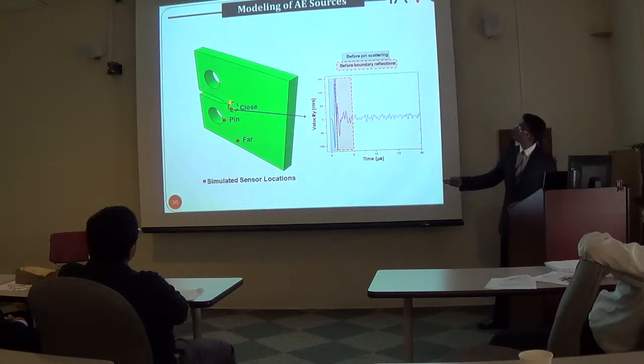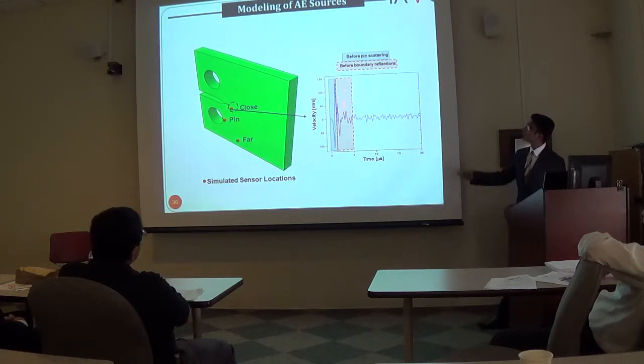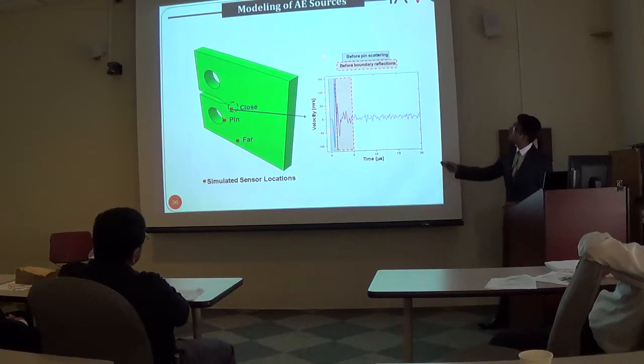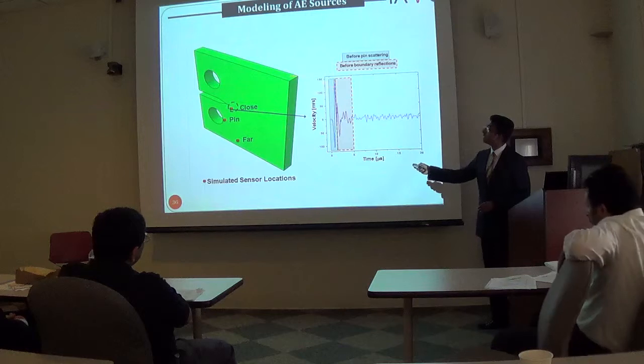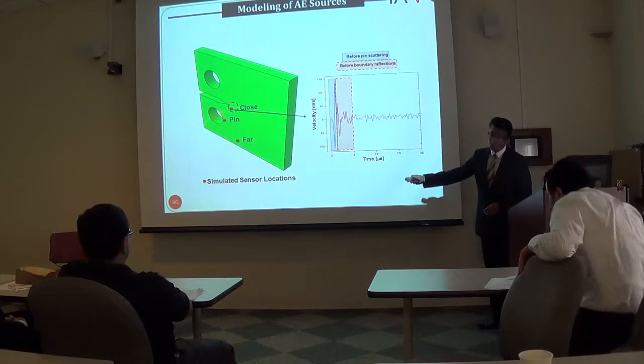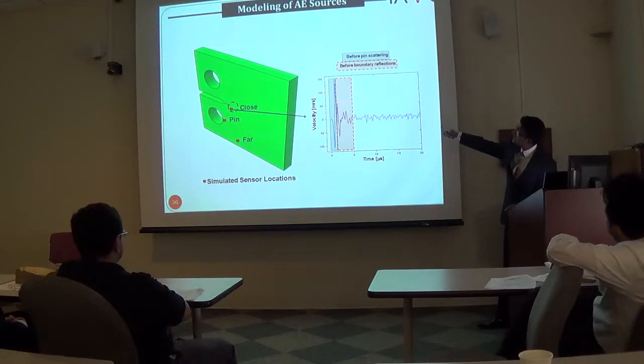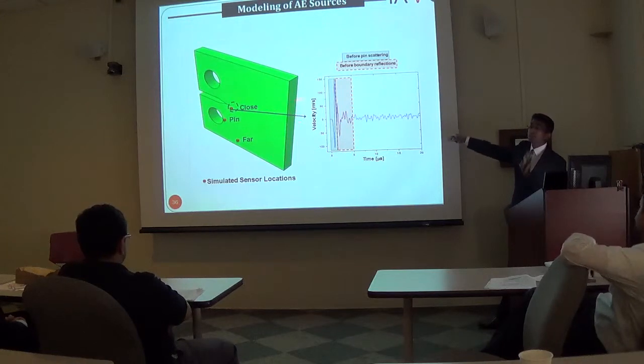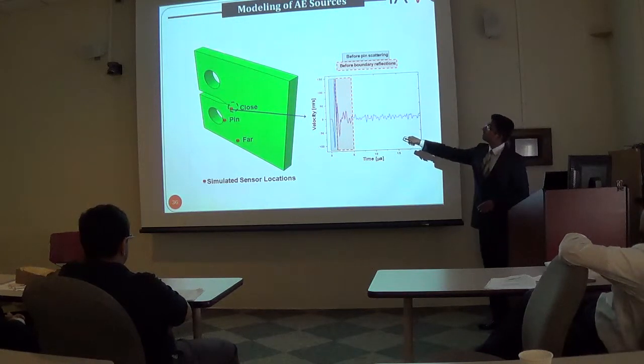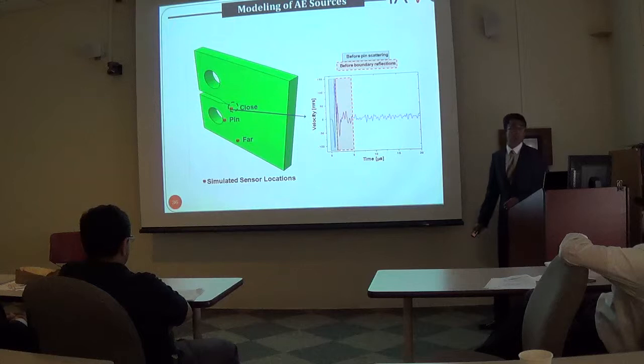You can see that the signal that was picked up right next to the crack was seen to have a burst type emission, with the initial packet having a very high amplitude. But upon the interaction of the waves with the pin, you see that the amplitude actually decreases, as you can note here. And this further decreases as it interacts with the geometry of the specimen itself.